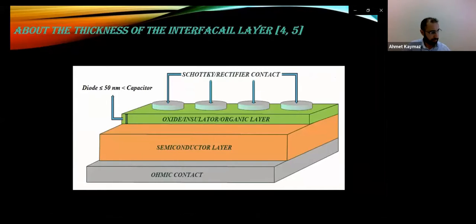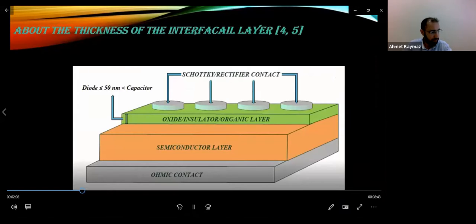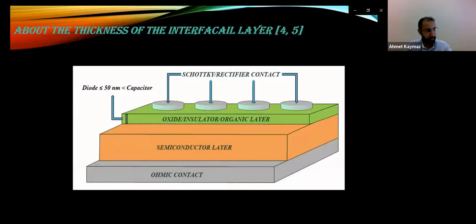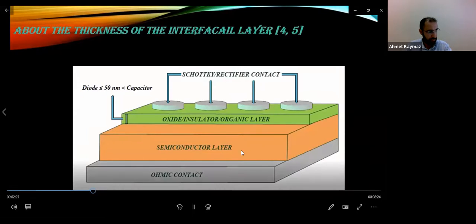By the way, I would like to mention an important point. If the thickness of the interfacial layer is thinner than approximately 50 nanometers, this structure can be used as a diode and is often referred to as a Schottky type structure or diode, due to the important work presented by Walter Hans Schottky. On the other hand, if the thickness of the interfacial layer is greater than 50 nanometers, this structure is called a capacitor rather than a diode.